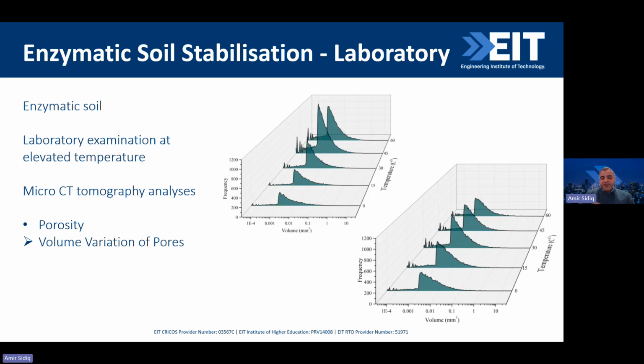Then here are some of the individual pore sizes. This is for the control or the raw material, and this is for the enzymatic. Here we can see this is the particular void size, and this is the frequency. So how many voids of this particular size are there for every pore within the entire sample? You can see here for the raw material, the frequency is going pretty high at different temperatures. And this is the same sample, just experiencing different temperatures. For the enzymatic, it is still increasing, but this increment is pretty similar. It's almost consistent. Again, it's controlling the behavior of the clay materials.